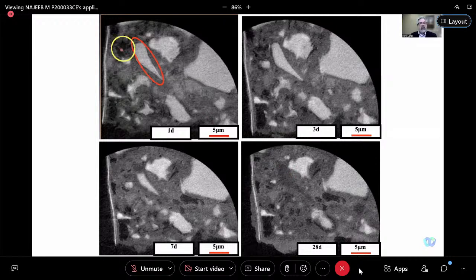This dark area by the yellow circle is filled in, so the hydration product has been deposited in that otherwise open area. Down here, there's a particle that doesn't change. Not every particle does react and dissolve at the same rate. Here we have a particle in green that now has an interface that is particularly high porosity. This was termed by Sid Diamond as being a Hadley grain, in honor of his grad student that wrote up the study that identified that feature.